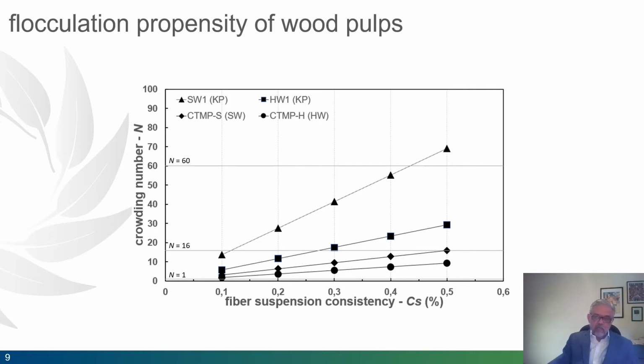Pulps containing softwood fibers are more prone to flocculation propensity, while in contrast, those containing hardwood fibers have less flocculation tendency, as shown either for kraft pulps and CTMP pulps. Softwood is primarily used for tissue paper structural reinforcement, since the higher aspect ratios can provide a stronger fiber network. But on the other hand, fiber collisions are likely easier to happen, resulting in great intensity of mechanical fiber entanglement.